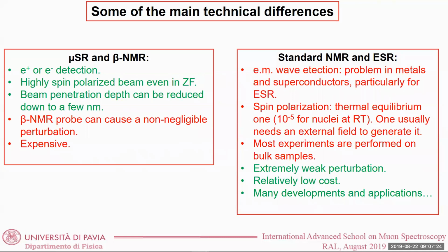I mean, we can probe the whole sample, the muons go through all the samples, and the positrons which are emitted, you can detect them very easily coming from all your sample. The other advantage is that in these techniques, MUSR and beta NMR, you are able to produce a highly polarized beam of particles, a spin polarized beam of particles, while in the case of ESR, or if you want NMR, the polarization comes from the thermal magnetization.